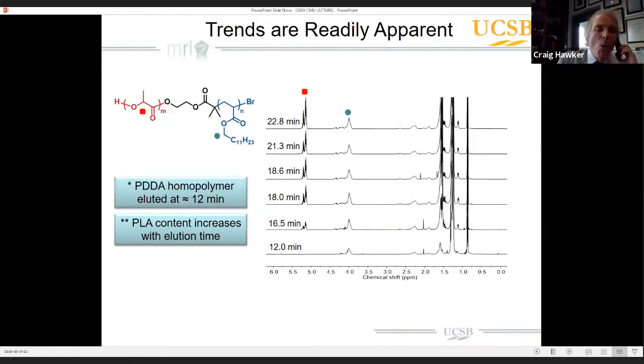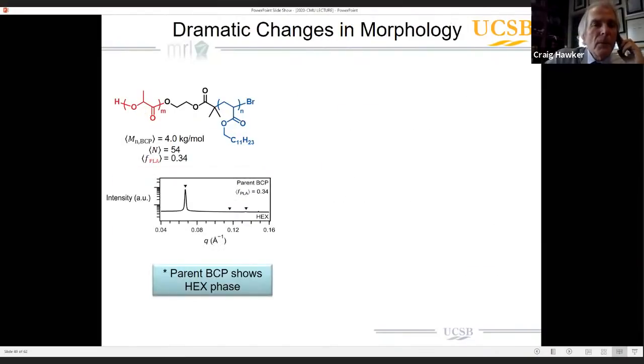We've characterized these using all the standard techniques, and it really is operating as I've told you. You see the fraction that we obtain at 12 minutes is that contaminant. It's the polydodecyl acrylate homopolymer. It has no lactide in it whatsoever. Then as we start to collect more and more fractions, you see that the amount of lactide increases significantly from the early fractions to the later fractions, directly correlating with the plot that I showed you before. So we now have the ability to make these polylactide polyacrylate libraries.